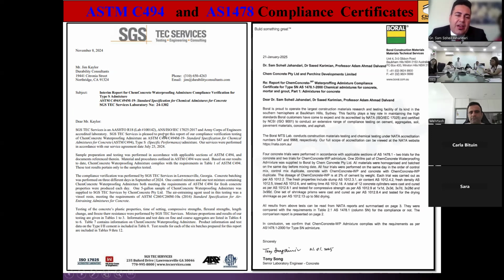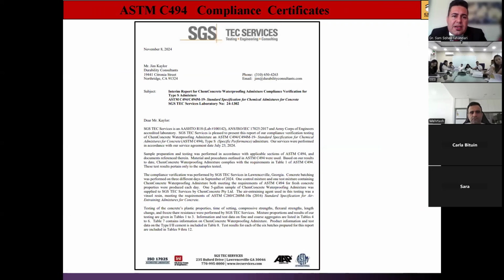Okay, sir. So we have received a compliance certificate with ASTM C494 from SGS TEC Services in Atlanta, and the product passed all the requirements of that standard. The product was also tested by Boral, which is probably the most well-known NATA accredited laboratory, and it also passed all the requirements of AS 1478. So two of the most widely used standards for compliance of these products.